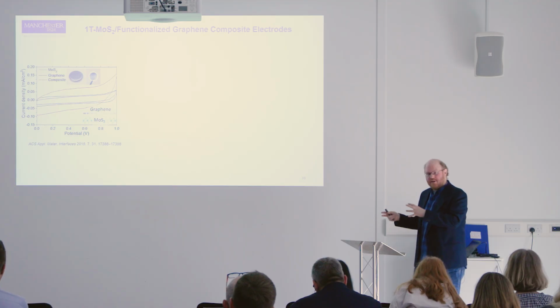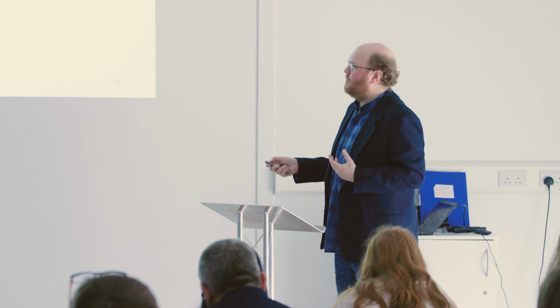Okay, so that's one way we can prevent restacking: functional molecules. As I said, the other way to do it is synergy between, say, multiple materials. So if we use graphene or MoS2 by themselves, their performance is not very good. If we mix the two of them together, we immediately get this synergistic improvement. That was work that we did quite a long time ago now, almost 10 years ago.